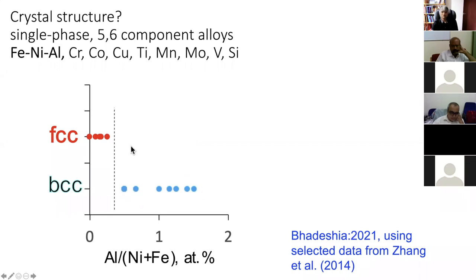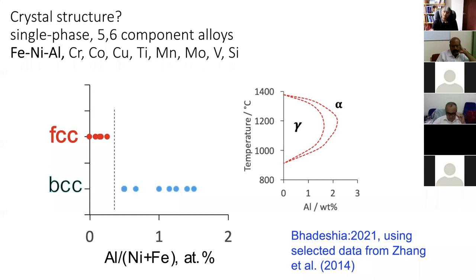Now, the number of points here looks less than in the previous slide, and that's because there's an awful lot of overlap of points according to this. Now, why did I decide to plot against aluminium divided by nickel plus iron? Well, that's a simple metallurgist thinking that when we add nickel to iron, we stabilize the FCC phase. But you recall that the aluminium phase diagram is quite dramatic in showing that it stabilizes the ferrite phase beyond a certain concentration. So it makes sense to me that if I add aluminium to a high entropy alloy, it will tend to become a body-centered cubic structure.